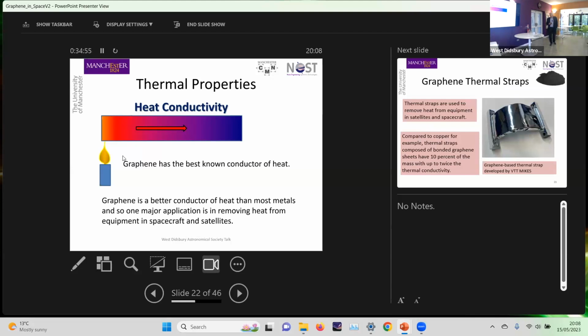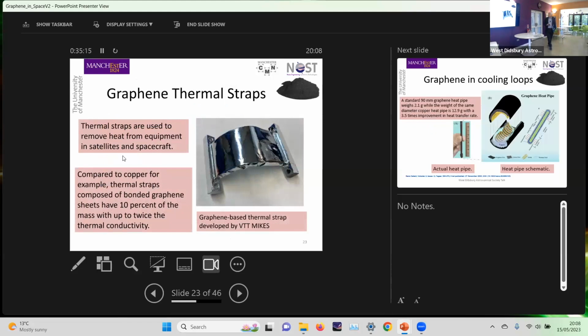So it's the best conductor of heat. It's a better conductor than most metals, and it's a lot lighter than most metals. And one of its major applications is in removing heat from spacecraft and satellites, where you've got instrumentation which needs heat removing from it. Graphene is very, very useful for that. So this is a thermal strap made for a satellite for removing heat. And this one is a graphene-based one. Current ones that are in use are copper-based. This is made from bonded graphene. It has 10% of the mass of a copper one, and up to twice the thermal conductivity. So it's twice as efficient at getting rid of the heat, and it's a hell of a lot lighter. So getting it into space costs you a lot less.